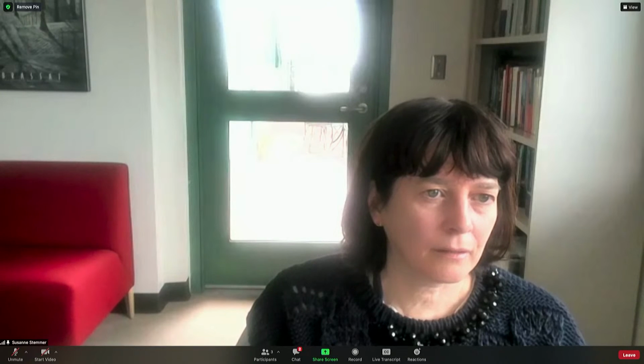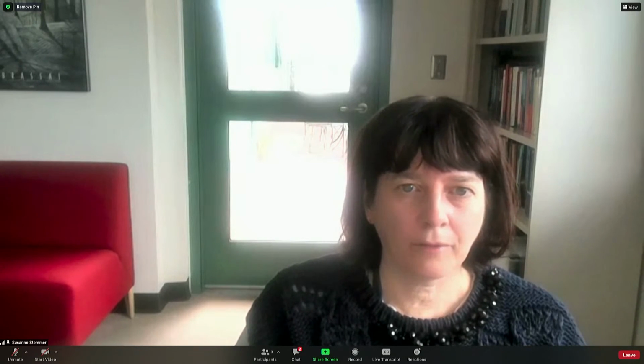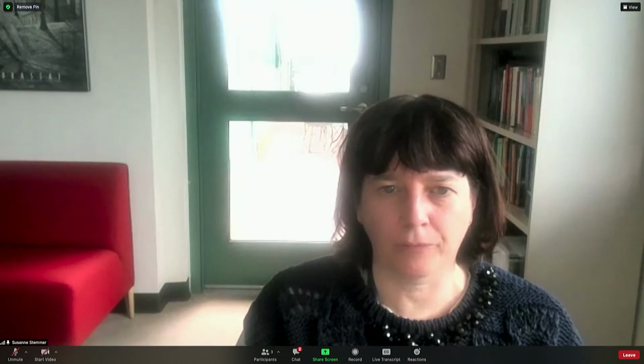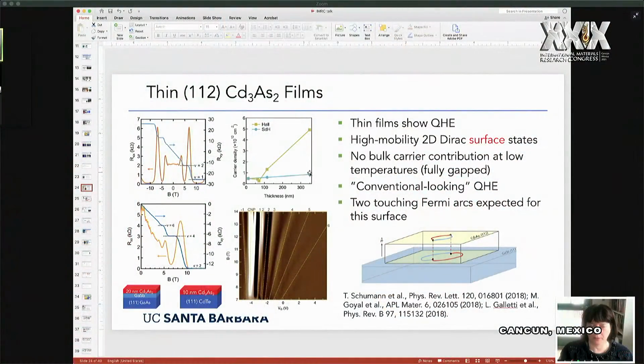So we did, I'm trying to find a slide. We actually looked for the 112 films. We looked at Shubnikov-de Haas oscillations, and you can see they're there for the 2D states, to fairly high thicknesses. We did not really look if our interpretation. So there's no quantum Hall effect because there are huge bulk carriers here. We don't really have a clean quantum Hall effect for those, but we do see the Shubnikov-de Haas oscillations from those surface states, even in fairly thick films. The problem is that there's a lot of parallel conduction from the bulk, so there's no clean quantum Hall effect for these very thick films.